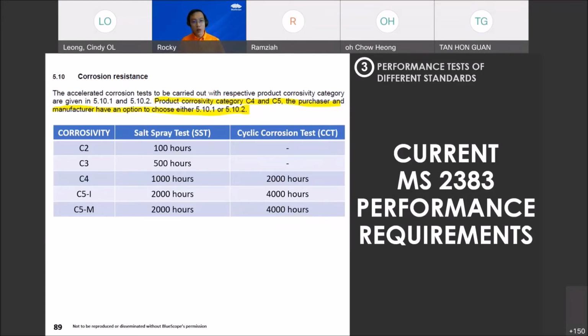And most often when testers like SIRIM conduct all these tests, just to put it in context, they charge by the hour, by how many hours you utilize the machine. For example, for 1 hour they could charge 10 ringgit. Then for salt spray test, it will be 10,000 ringgit for those 1,000 hours. Same thing, they would also charge 10 ringgit per cyclic corrosion hour, so that would be 20,000. So if you are a manufacturer, you are incentivized to conduct a shorter amount of test hours, because you pay less for the same classification of product. I can conduct salt spray tests, pay half the amount, and classify as C4.